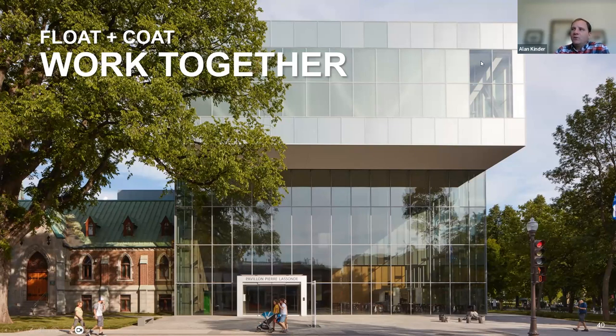If we look above, we've got vision units in these four panes here. And so we can start to see those steel structures, high VLT, low reflectivity, extremely transparent piece of glass, light coming from multiple angles to brighten that space. Here, where it looks a little more translucent, it's actually an additional coating added on surface number three that is an acid etching. And so that diffuses the light transmission. It doesn't change the actual level of light transmission. So it's still just as bright behind this glass, but because you have thousands of little scratches on that glass, you're refracting the light and you're creating more of that diffused, softer look, almost kind of a lantern look.